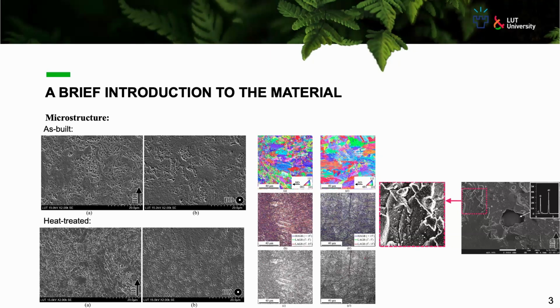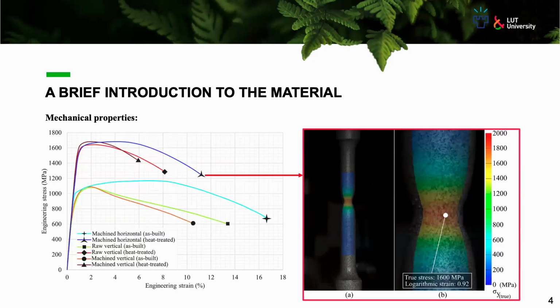So these are the general aspects of the microstructural features of this material after additive manufacturing and after the heat treatment that is designed for this powder. And as you can see, the effect of heat treatment on the quasi-static mechanical properties of these materials is significant. It causes a huge increase in the strength values from around 1,100 megapascal to close to 1,600 megapascal. And even after heat treatment, as is shown here, the ductility and elongation to failure of the material is significant. As you can see in this DIC image, even the heat-treated sample showed a very significant necking phenomenon before its final rupture.